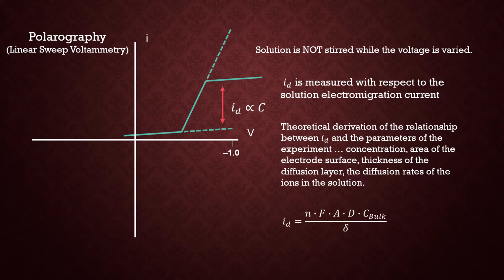So again, as I stated, the theoretical derivation, you have this as one possibility. I'll draw your attention to the denominator here, and that is the diffusion layer thickness. So this is why when you stir versus not stirring, the current will continue up in that linear fashion. So think about this in terms of that thickness. If that thickness goes to 0, which is the case when you stir the solution more violently, you decrease the unstirred layer at the electrode surface so that the resultant diffusion current is actually going to increase, and you're going to get that linear off to infinity type thing. So that's why there's a difference between stirred versus non-stirred electrochemical experiments.